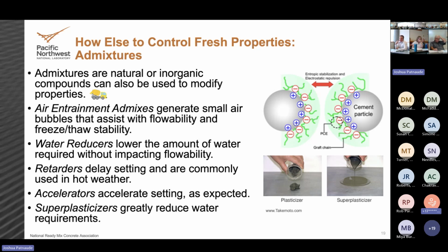What admixtures are designed to do is, if we can't get ideal processing by the introduction of fly ash or blast furnace slag, or maybe our waste chemistry isn't ideal, we can add in different chemicals to accelerate or slow down those hydration reactions. One of the main processes that admixes do is you can think of it as they can act as set retarders, so they can protect the cement particles and avoid water from getting to them. If water doesn't get to the cement particle, it can't dissolve, it can't be involved in those hydration reactions. So when you put a superplasticizer, a set retarder in, it's an organic compound, goes in, finds the cement particle, coats it, and it will slowly dissolve and water will slowly get to the particle and you will slow down those rate of reactions, therefore slow down your set times.